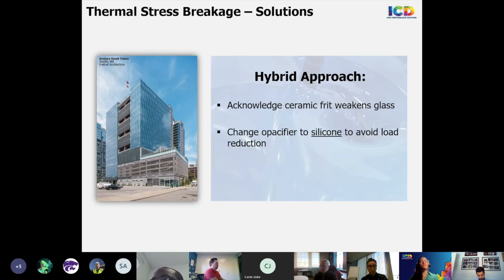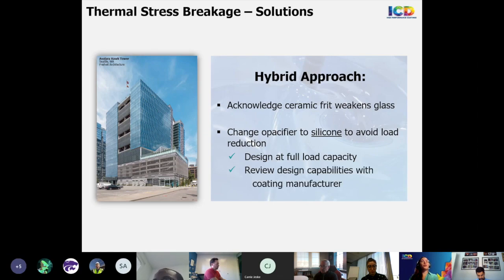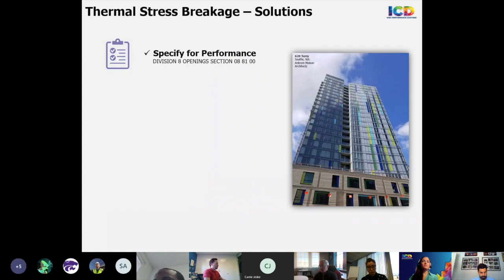You can also change the opacifier to silicone to avoid this load reduction completely and design at full load capacity. But you should always review design capabilities with the coating manufacturer. Silicone coatings cannot be screen printed like a ceramic Frit. It's only for the full flood coat applications for Spandrel.